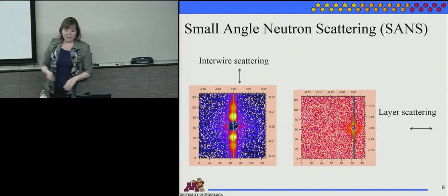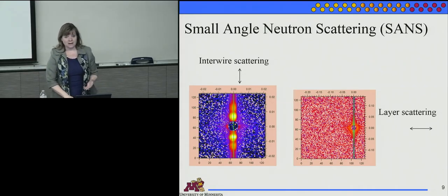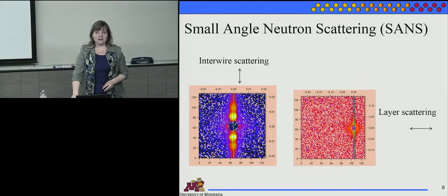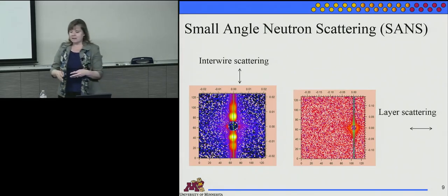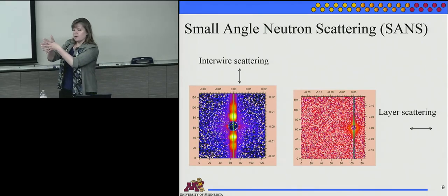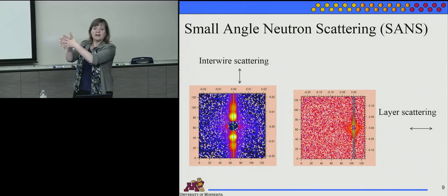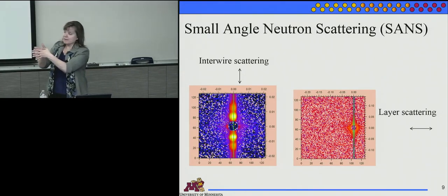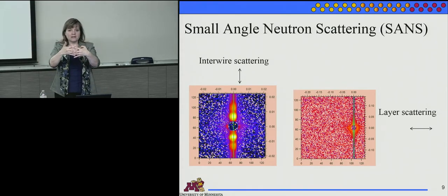And this is something I just want to point out. The paper's coming along. Our NIST collaborators are working on that. But it turns out the idea, let's say that I have a nanowire with pancakes, which is, this is one nanowire represented right here, and my fingers are the pancakes of cobalt. If you magnetize it that way, we've thought when you go back to zero field, they're antiferromagnetic.